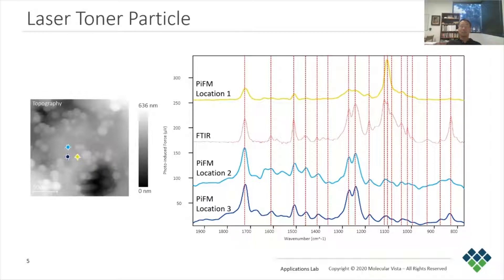In this case, we can see that the bulk FTIR consists of spectral features from the three nanoscale PIFM spectra. Location 1 in yellow contributes primarily the peak near 1100 wavenumber, whereas locations 2 and 3 contribute the peaks near 1460 and 830 wavenumbers respectively, along with many other common peaks. For samples that have nanoscale inhomogeneity, the PIFM spectrum will represent the local chemical state, whereas the bulk FTIR spectrum will represent the sum of all the local chemical states.